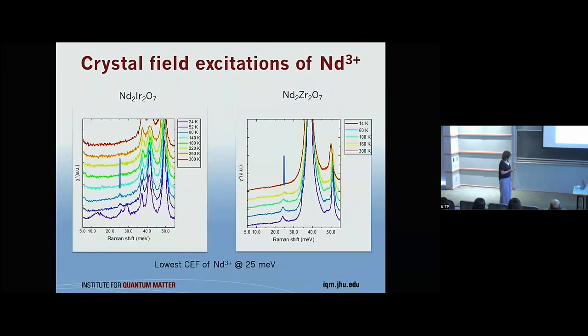So then we thought, okay, what is left? There are no phonons. There are iridium excitations already there, so we can look at what's going on with the neodymium sublattice. The first thing to think about is that it could be a crystal field excitation of neodymium, which is somehow dramatically enhanced. And the answer is no. For neodymium iridate, crystal field excitations were measured with very low resolution by neutron scattering. It has the same site symmetry and a very similar environment to neodymium zirconate, so that was an additional thing to compare.